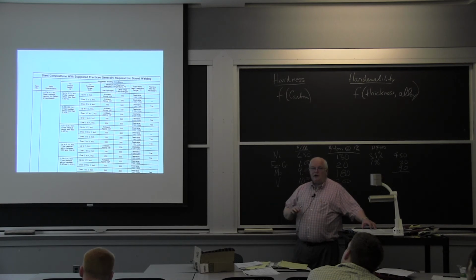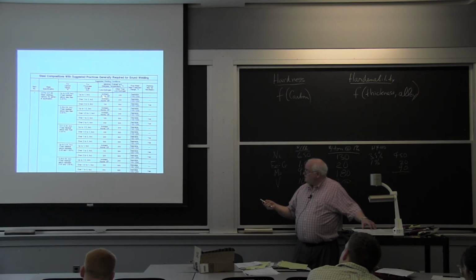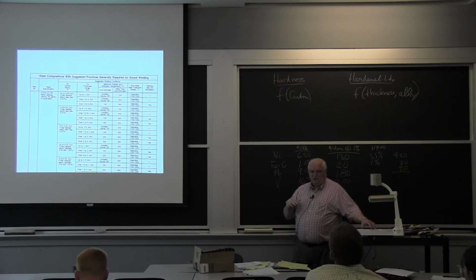Okay, actually the ASME code says you have to be above 50 degrees Fahrenheit, which is actually much better because you get rid of all the moisture. At 10 degrees Fahrenheit, I could have frost on there, right? Now I'd be burning the frost off as I weld along, but nonetheless, the ASME code says you cannot weld if your plate is less than 50 degrees Fahrenheit.